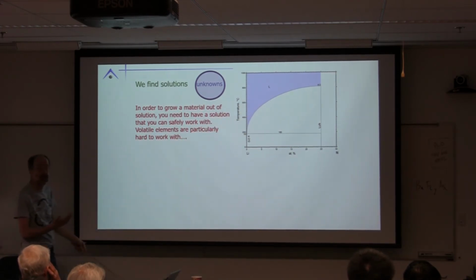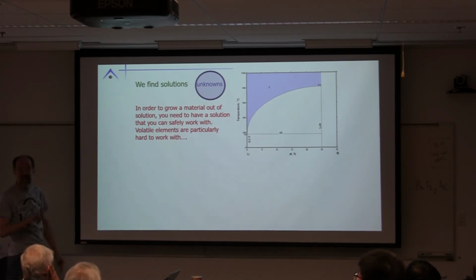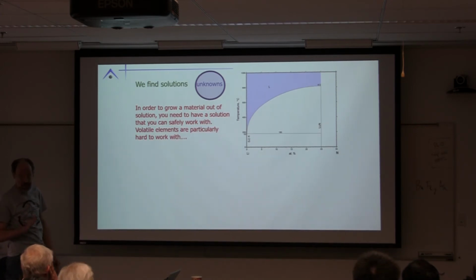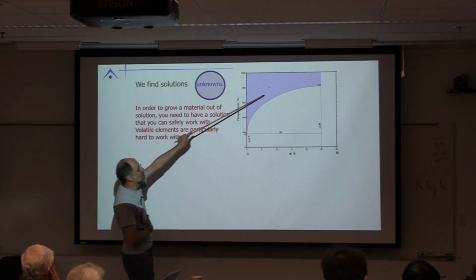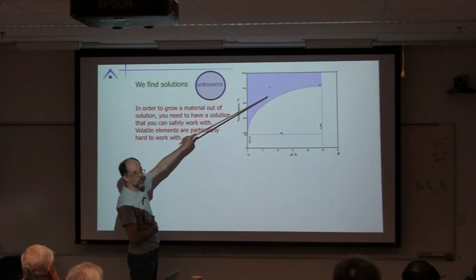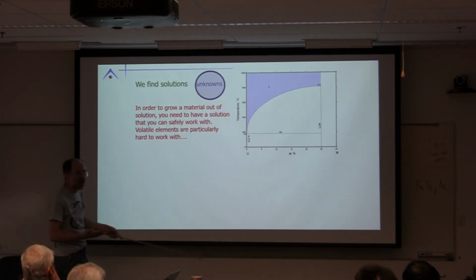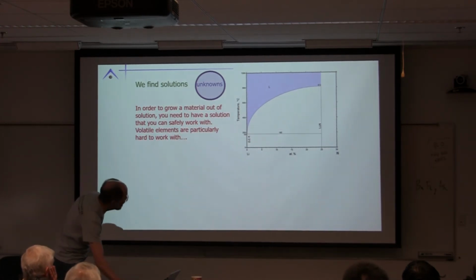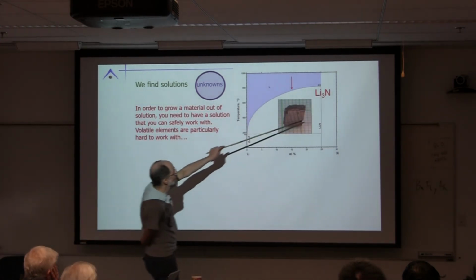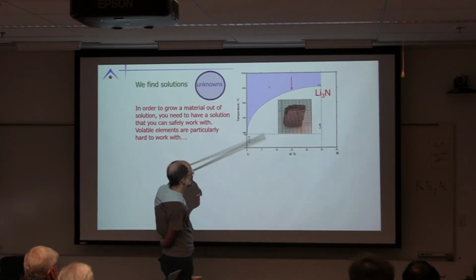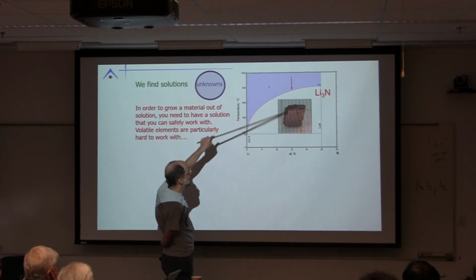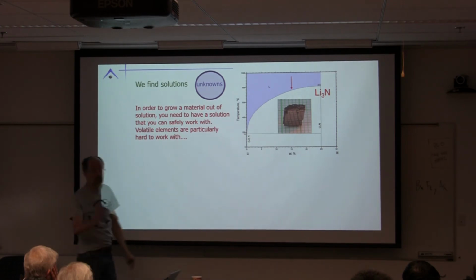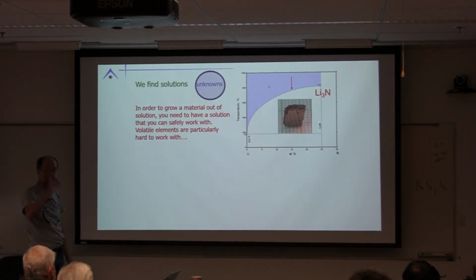Now there's a similar lithium nitrogen binary. It's calculated, not experimental. And when you do that, you end up finding out that this is a liquid plus nitrogen gas and things blow up. So I approached this very carefully and we sort of saw what we could do. So I got lithium 3 nitrogen powder, dissolved it into lithium, and then cooled down, and we could get huge, beautiful single crystals, which means you actually can have atomic nitrogen dissolved into lithium and you can grow things out of it, which is lovely.